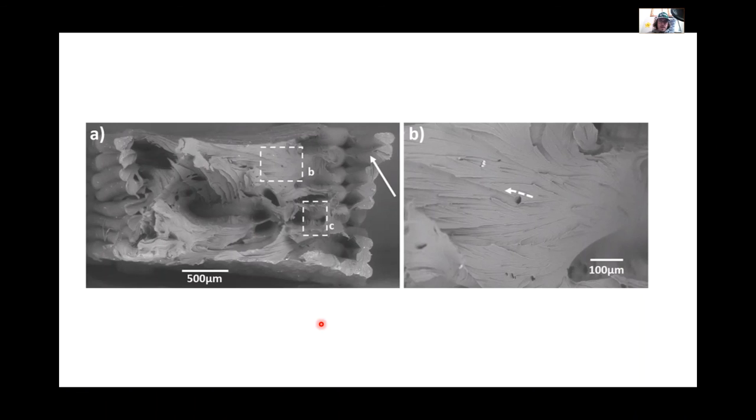This is another thing I kind of want to show. So this is PETG again. You can tell a lot of plastic deformation, but this void here did not play a part in the failure of this material, basically, is what I'm trying to show. And so not all defects in a polymer specimen play a role in the overall failure. And I've kind of argued this with people now and again, but this is due to viscoelastic flow. If it's big enough, okay, it'll cause some problems, and we've seen that earlier in this lecture.